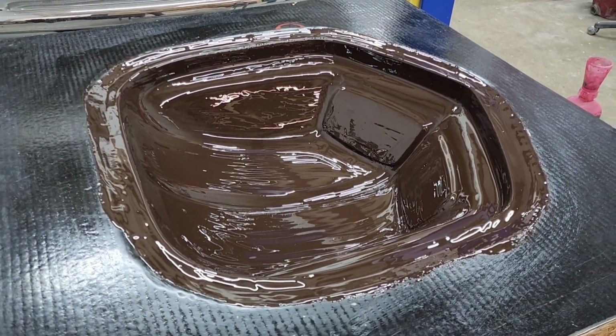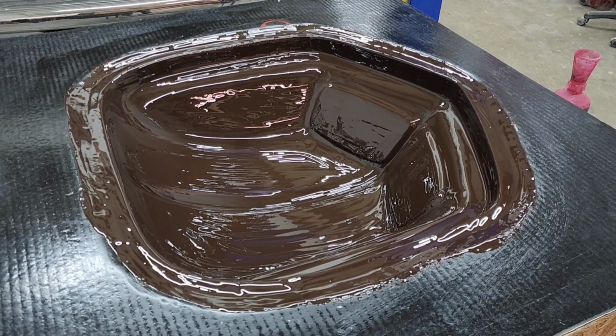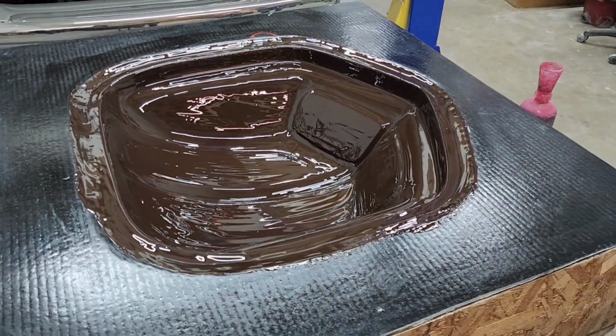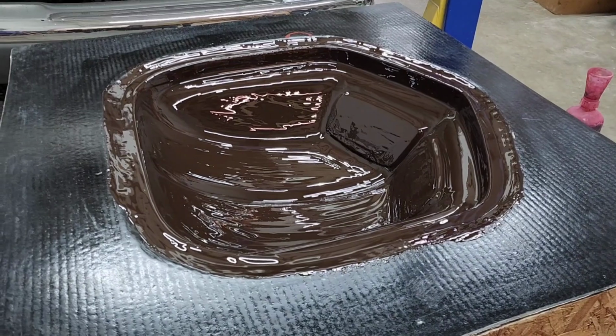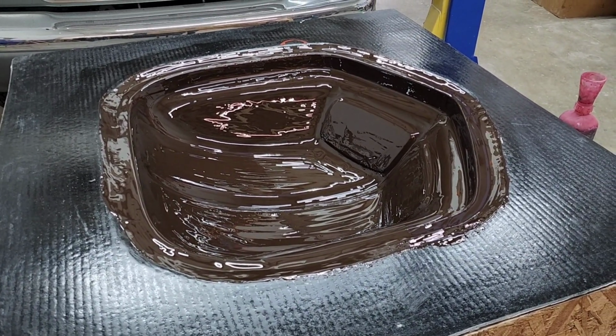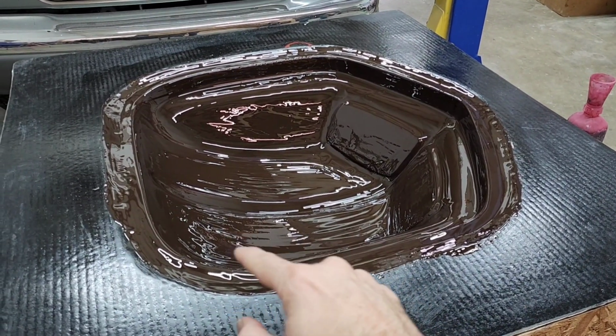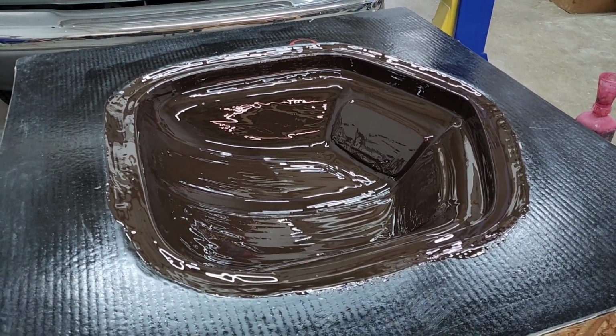As I said, if it's thicker, it can cure faster, and you want it to be all the same thickness so that it cures at the same time. If you get into where it's different thicknesses on the mold, it can cause lifting problems where, you know, you'll get almost a bubble that'll lift off the mold, and you don't want that.